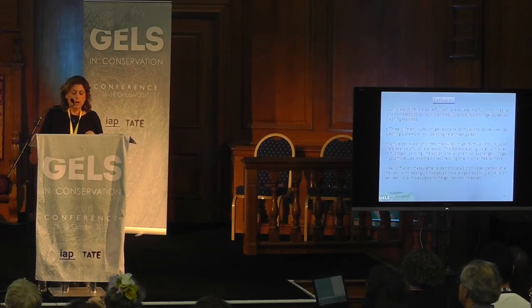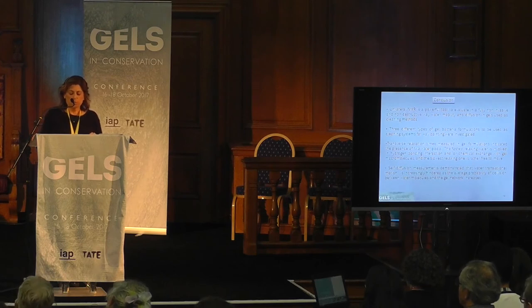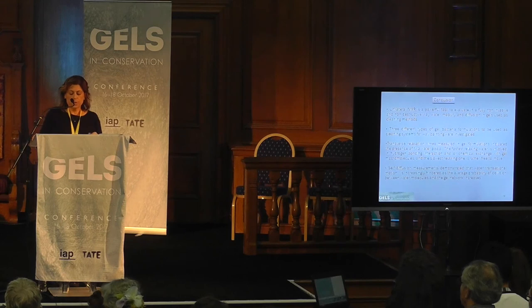In conclusion, unilateral single-sided NMR is a powerful tool to evaluate in a fully non-invasive and non-destructive way water mobility and diffusion in gels used as a cleaning method. Three different types of gel-bacteria formulations to be used as a cleaning system for wall paintings were investigated. Transverse relaxation times measured in gel formulations indicate the presence of two water pools: the fastest relaxing water is involved in hydrogen bonding interactions and/or chemical exchange with gel macromolecules, and the slowest relaxing one is rather free to move. Self-diffusion measurements demonstrate that the water translational motion is increasingly hindered as the average probability of collision between water molecules and the gel network increases.